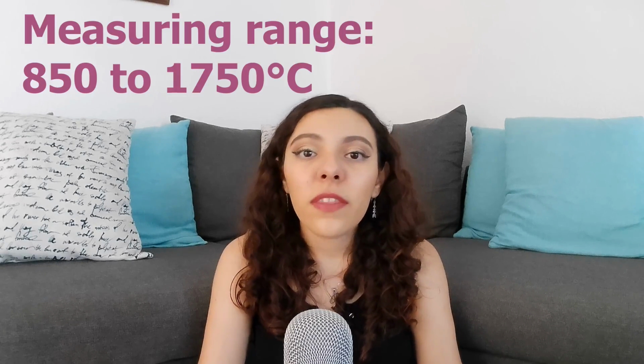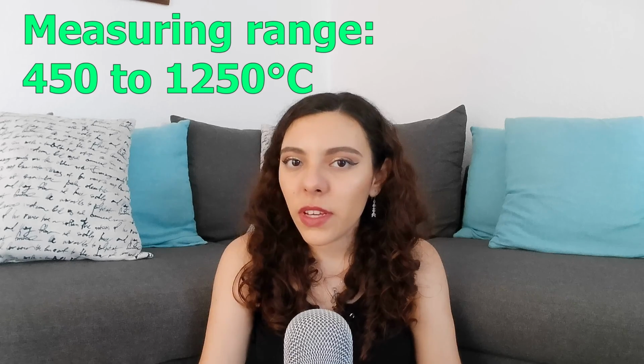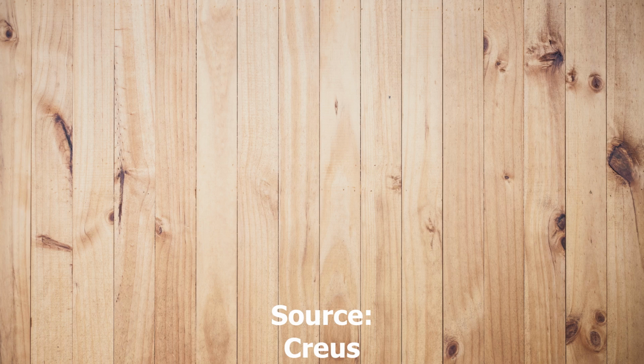Pyrex lenses are used in the temperature range of 850 to 1750 Celsius, fused silica lens in the range of 450 to 1250 Celsius, and calcium fluoride lens for lower temperatures. In this graph, we can see the distribution of radiant energy. It can be seen that the visible radiation represents the area between 0.4 and 0.75 microns, that Pyrex lenses allow the passage of waves from 0.3 to 2.7 microns, that those of fused silica allow waves of 0.3 to 3.5 microns to pass through, and that of calcium fluoride, they do so up to 12 microns.